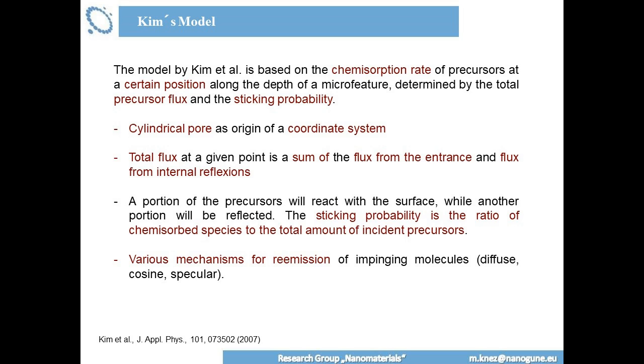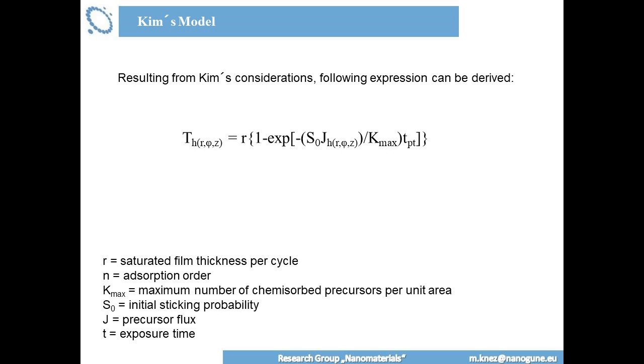Now, it's a little bit of a different view, so you also have to consider the flux at a given point, and you have to consider the sticking probability, so the ratio of the chemisorbed species to those which do not chemisorb. He also considered, which was very nice, various mechanisms for re-emission. That means not all of the molecules will really bind directly, some of them will reflect and some of them will bind. So all of this is put together in this paper, in the derivation of this formula. And at the end, you will end up with something like that. So the time for the exposure here is in the exponent of the dosing time.